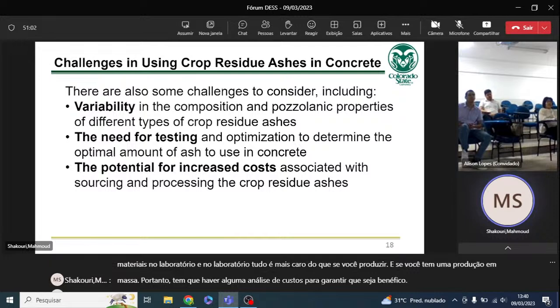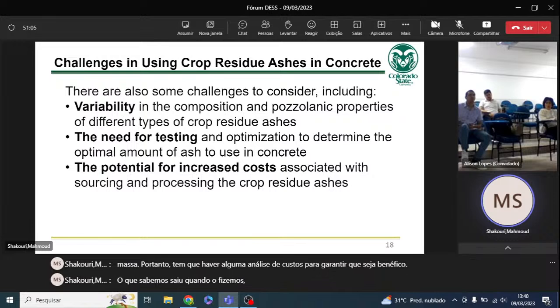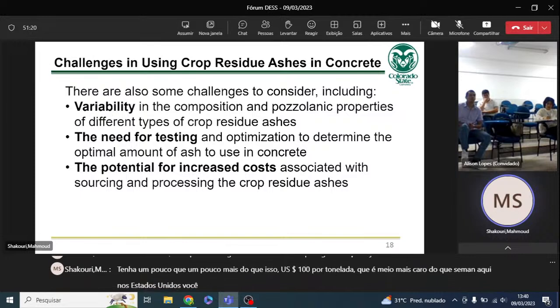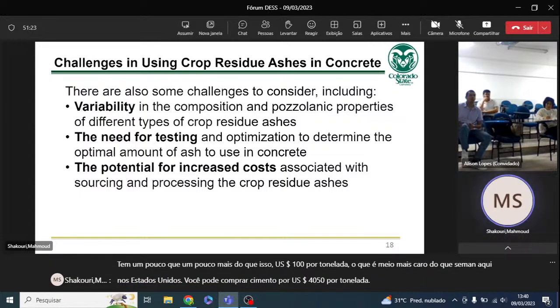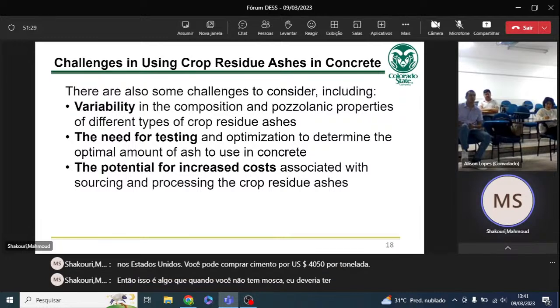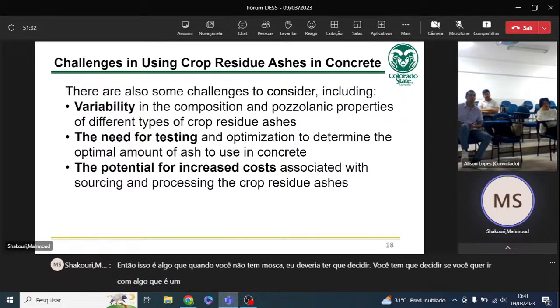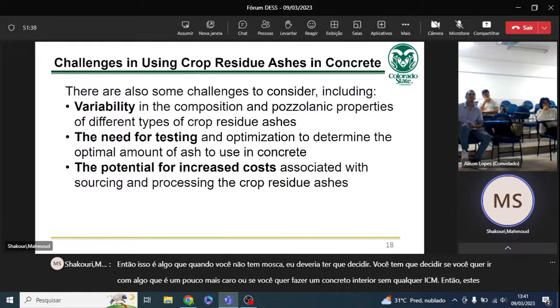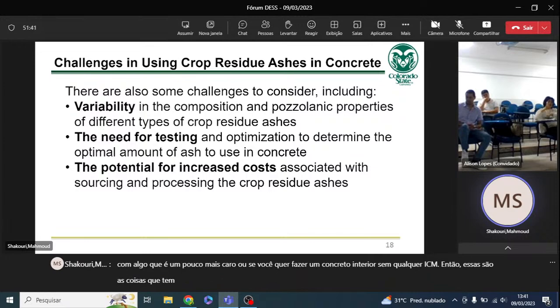What we came out with when we analyzed our products was that we can produce these at a little bit more than $100 per ton, which is kind of more expensive than cement. Here in the United States, you can buy cement for $40-50 per ton. So that's something you have to decide when you don't have fly ash. You have to decide if you want to go with something that is a little bit more expensive, or if you want to make an inferior concrete without any SCM. So these are the things that have to be decided before committing to producing these materials.